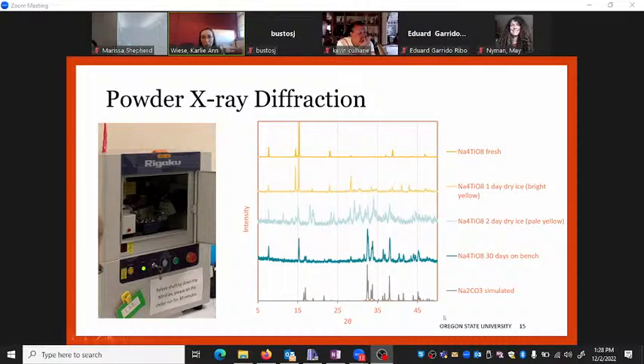And then one interesting thing that we discovered here is that the sample that had been on the bench and the simulated PXRD for sodium carbonate have a lot of similarities in their peak positions. And so that's telling us that probably we have some sodium carbonate that's formed within our structure. So another good indication of how the CO2 is combining in the material.